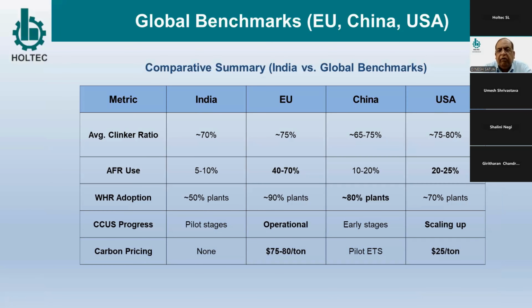Just to get a global perspective with respect to India, EU, China, USA, if we talk of average clinker factor, it is around 70 India, 75 EU, China 65 to 75, USA 75 to 80. AFR use is around 5 to 10% in India, which is quite low and catching up now. EU is 40 to 70, China is 10 to 20, US is 20 to 25%. WHR adoption has picked up in the last many years. 50% of plants are now having WHR, 90% in EU, 80% China, and 70% USA.